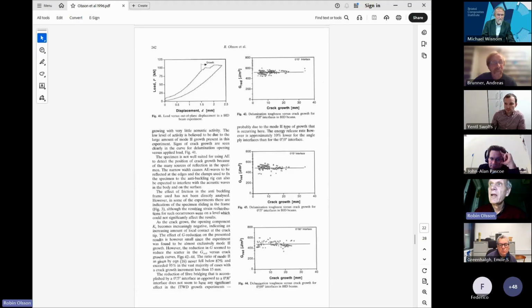So it still agrees with the reasoning of Emil that if you don't trap your delamination growth between 0-degree plies, then you get migration and you don't get this kind of delamination growth. But I thought it was interesting that you can get stable values which are all much lower than the initiation values you see in a conventional ENF test.